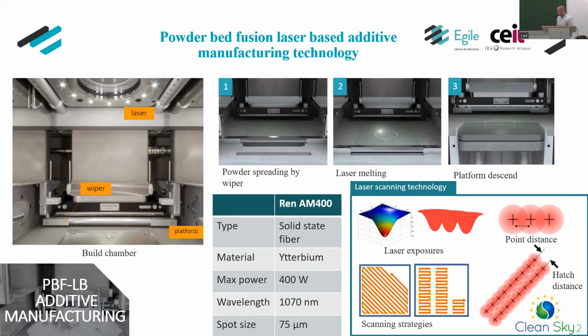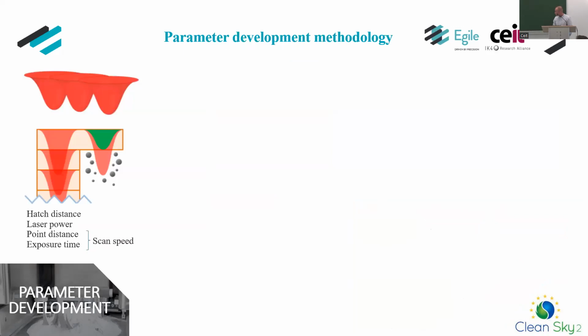If you look at this picture, you can see a Gaussian distribution of energy density in the melting of the powder. By changing many different parameters, we will be working with different energy density levels in the melting of the powder. The main parameters we've checked in order to develop these laser scanning parameters have been the hatch distance, which is the distance between the scanning lines, the laser power, and the point distance and the exposure time between these exposures that determine the scanning speed of the laser.